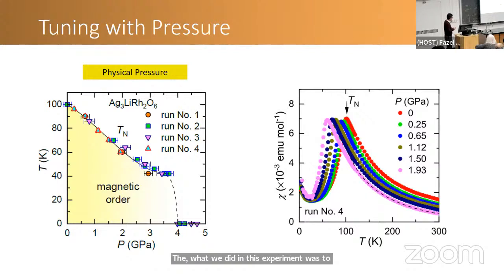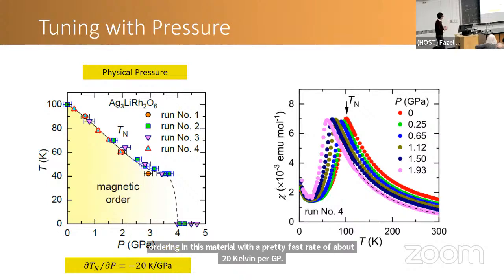The peak here in magnetic susceptibility represents the magnetic transition temperature. And with increasing pressure, that transition basically went down to smaller and smaller values. And so we saw a very rapid suppression of magnetic ordering in this material, with a pretty fast rate of about 20 Kelvin per GPa. It's a really quick rate, actually. And so this was a very exciting experiment.